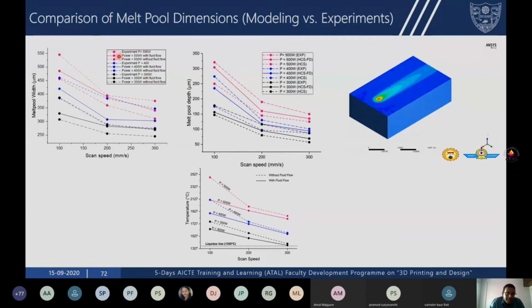So if you consider the three red color indices here, the first one is the experiment at 500 watts. Then the solid line is with fluid flow, and this is without fluid flow. You can clearly see that the one with fluid flow is in better agreement with the experiments compared to the one without the fluid flow. So incorporating fluid flow becomes very important when you are trying to predict the shape of the molten pool, the maximum temperature, as well as the residual stresses. As I said, when you neglect fluid flow, you are going to over predict the temperatures, because you are not considering the convective flow in the melt pool. You are going to over predict the cooling rates as well as the thermal gradients.